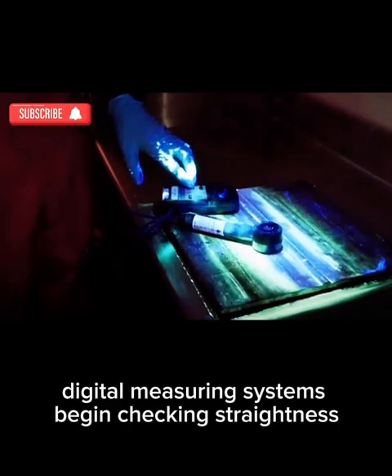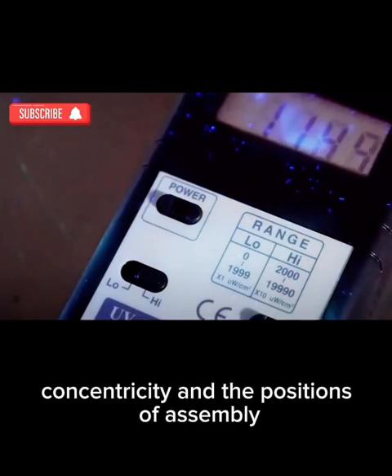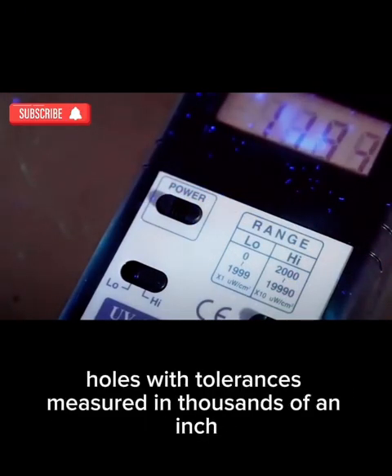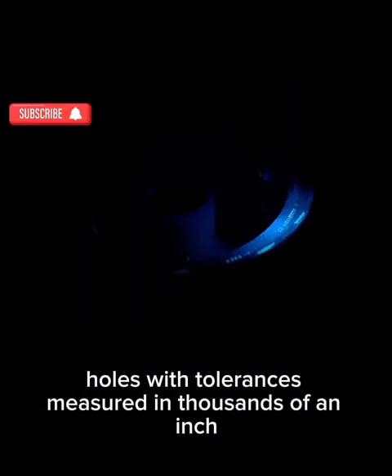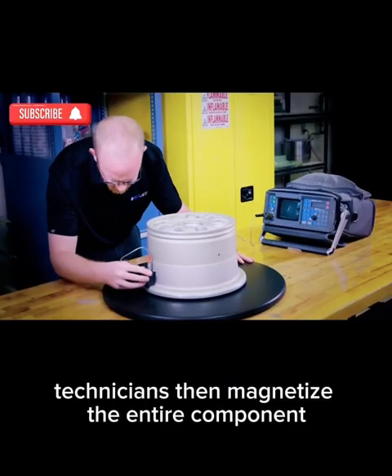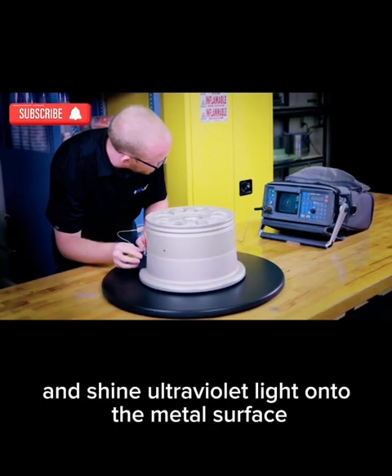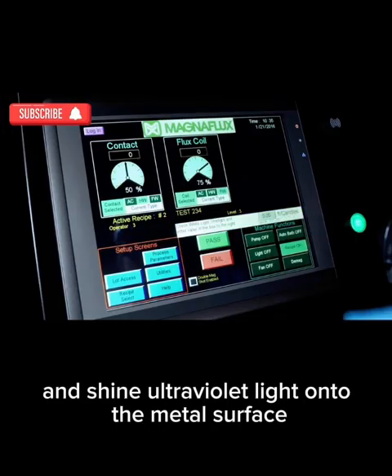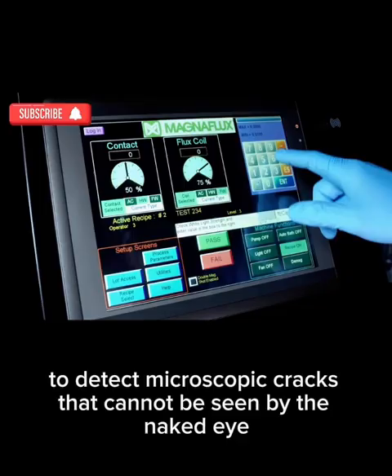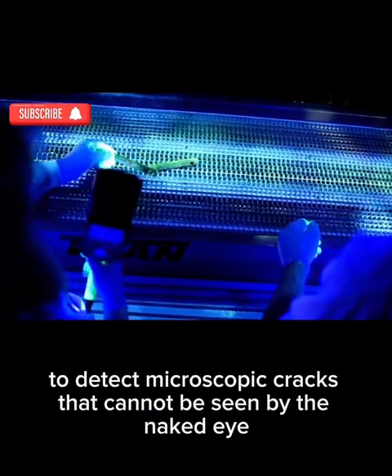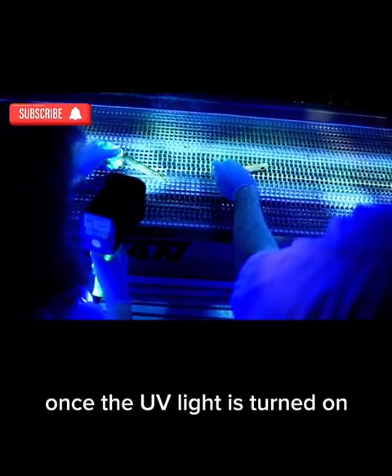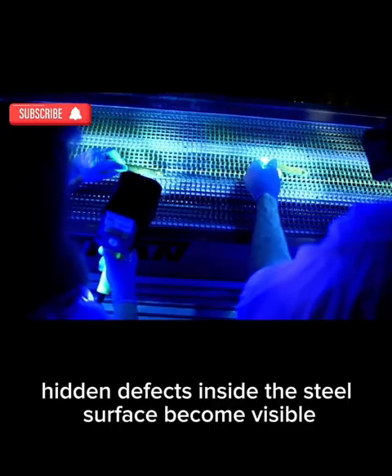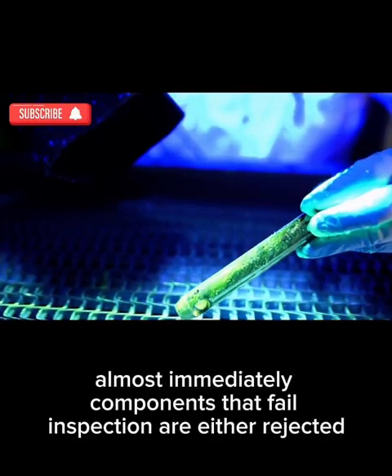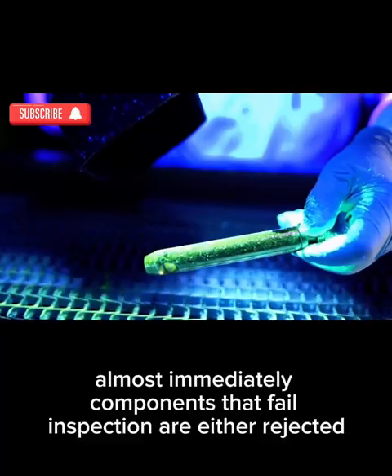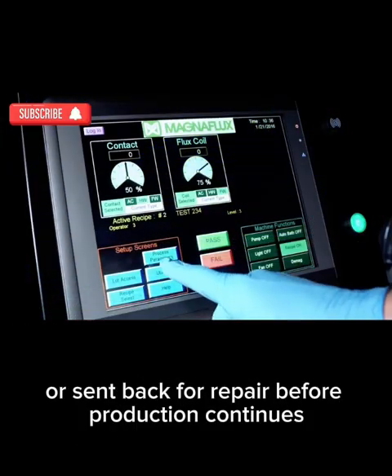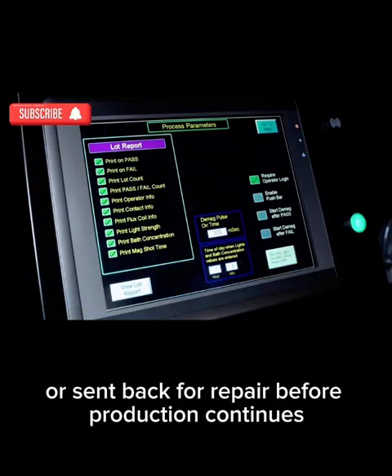Digital measuring systems begin checking straightness, concentricity, and the positions of assembly holes with tolerances measured in thousandths of an inch. Technicians then magnetize the entire component and shine ultraviolet light onto the metal surface to detect microscopic cracks that cannot be seen by the naked eye. Once the UV light is turned on, hidden defects inside the steel surface become visible almost immediately. Components that fail inspection are either rejected or sent back for repair before production continues.